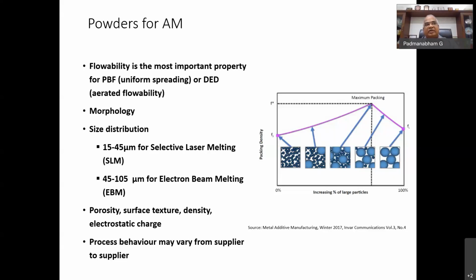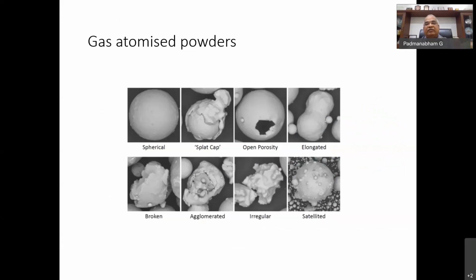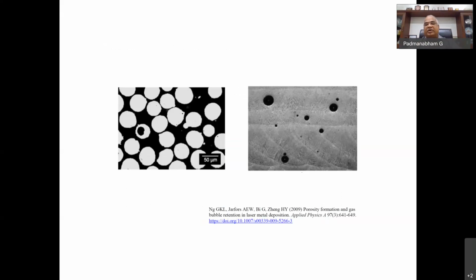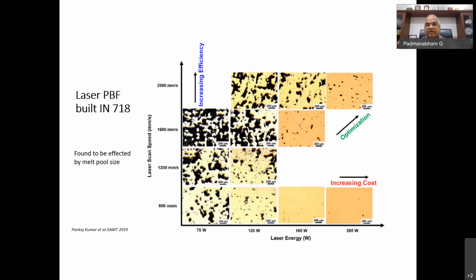And then the powders are produced and supplied by different suppliers from all around the world. We found that there may be a variation in the process behavior from supplier to supplier also. We have seen that. So this is another challenge. And within the powders, what should be the quality of the powder? These are all the defects that we encounter when you look at the powders, like open porosity, and satellites of small powder particles on the bigger particle. For example, when you use open porosity particles, you end up with porosity in your part. When you use satellited particles, you end up with higher surface roughness, and it is difficult to manage your surface finish.